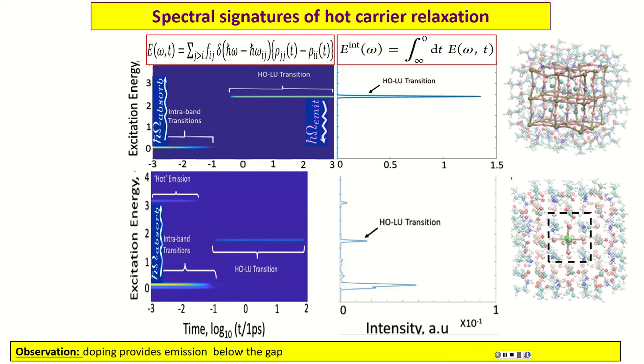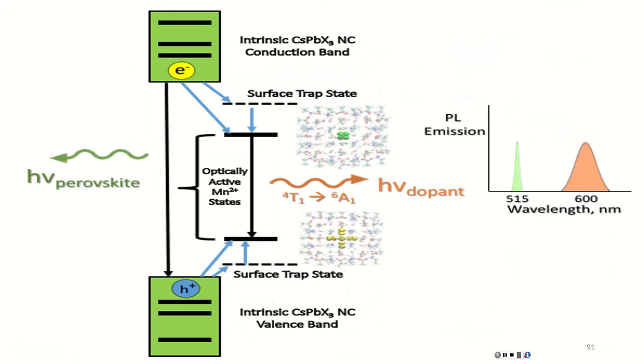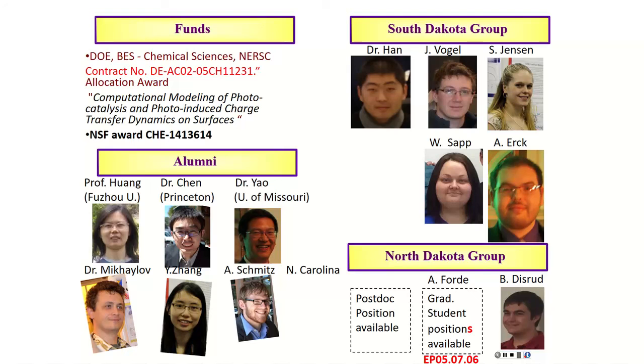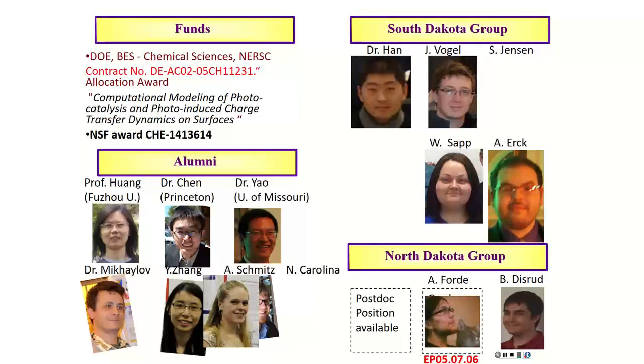And probably the problem is that single determinant DFT is not the best choice for these excitations for transition metal. Or maybe something else is missed. So just plain addition of spin-orbit could be insufficient. Maybe taking excitons into account would solve this problem and would make this transition brighter. There are some additional effects, so it is an open problem. But in one experiment, this one is brighter than this one. Well, it's an old slide, now there is much more migration.